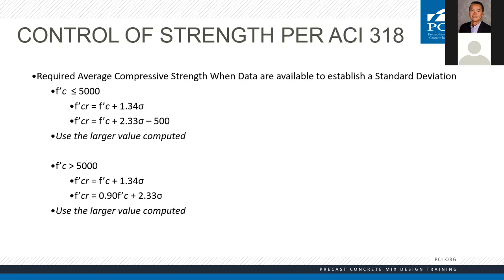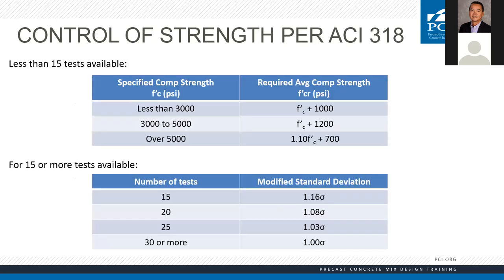I'll show you in the Excel spreadsheet — it will be clearer. If we have less than 15 tests available, our mix has to be 110% of our design strength plus 700 PSI. So with a 7,000 PSI design strength and fewer than 15 tests, the average would have to be 8,400 PSI. If we have more than 15 test points, we can use the standard deviation to optimize the mix and bring down that required strength. With 30 test points, we don't have to modify our standard deviation at all, allowing us to optimize our mix to a greater extent.